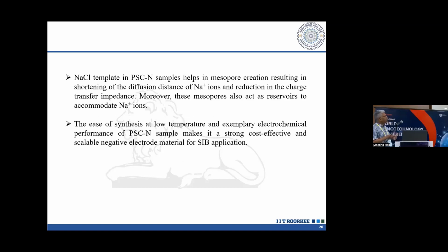And then we can talk about the sodium chloride template in this sample, which helps in this mesopore creation, resulting in the shortening of the diffusion path, because this is also important. If we have a shorter path of diffusion, we have a good rate control. And faster rate is very important in the sense that when we talk of electric vehicle charging and discharging, we cannot wait for hours together. Very fast charging should take place. So therefore, rate control is one of the very important factors of this kind of ion energy storage material like sodium-ion battery. In future, we have other types of battery, potassium-ion battery, zinc-air battery, aluminum-air battery, and those things. Of course, we are moving through the lithium-ion battery system now.